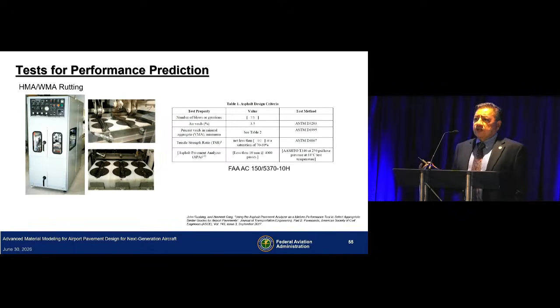Around 2006, 2007, we worked with the manufacturer of the asphalt pavement analyzer to develop an APA where we could apply 254 PSI. Because if you look at FAA advisory circular 150/5370-10, we moved from Marshall mix design to SuperPave, but there was no performance criteria listed. So we developed this APA, and Dr.